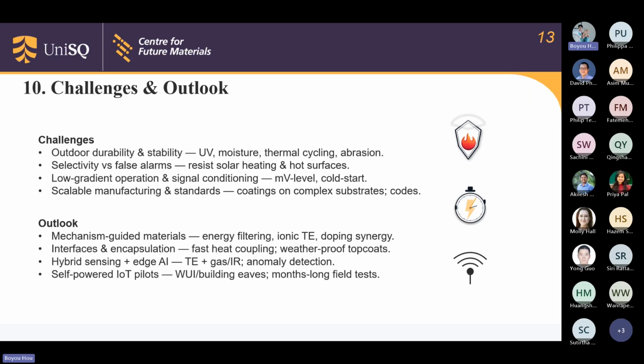With these challenges in mind, the path forward is clear. Mechanism-guided materials combine energy filtering, ion thermoelectrics, and tuned doping, with stability as the first requirement. Interfaces and encapsulation speed up heat coupling; use weatherproof char-forming topcoats for protection and repeatability. Hybrid sensing with AI: fuse thermoelectric with gas or infrared sensors. Run anomaly detection at the edge to cut false alarms.